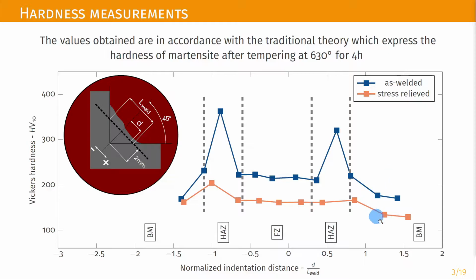In this graph, you can see the hardness curves around the weld seam region, both for as-welded and stress-relieved specimens. The hardness values were plotted over a normalized indentation length, the definition of which can be observed at the top left corner of this figure. As can be seen, the hardness decreases after the heat treatment and settles down to values traditionally expected for a stress relieving process of a structural steel.